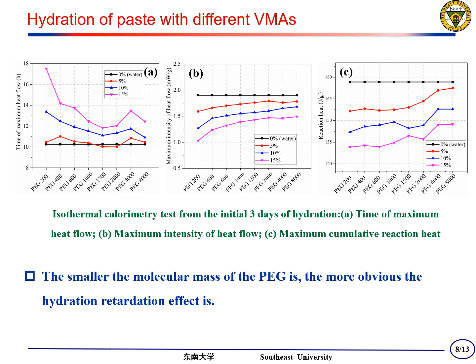Meanwhile, the PEG added for the purpose of inhibiting ion transport will inevitably inhibit the diffusion of cement hydration products, forming a high concentration range of hydroxide around cement particles and retarding hydration.